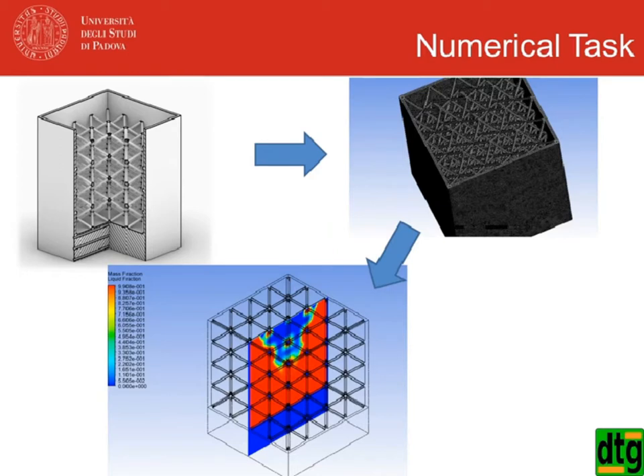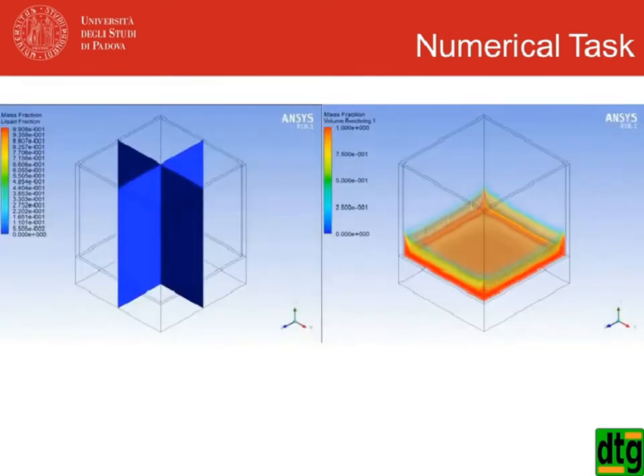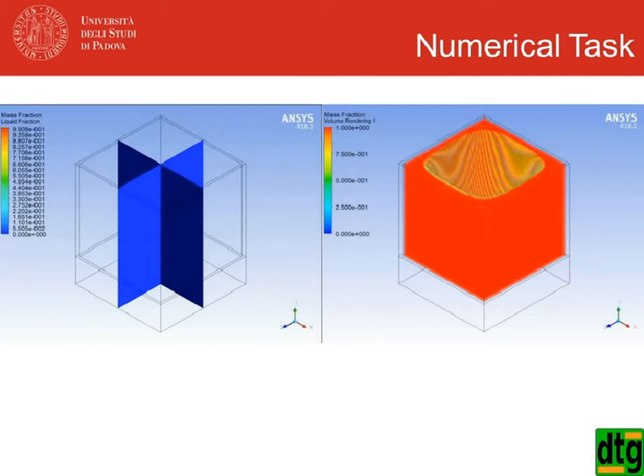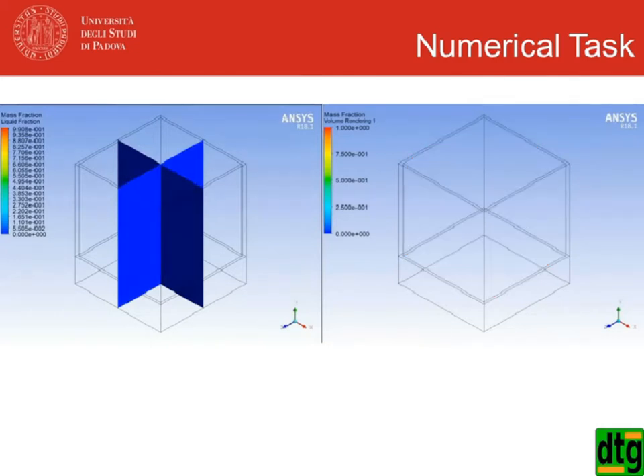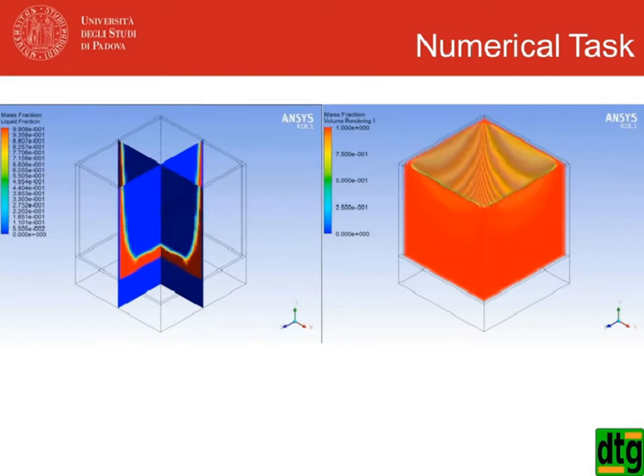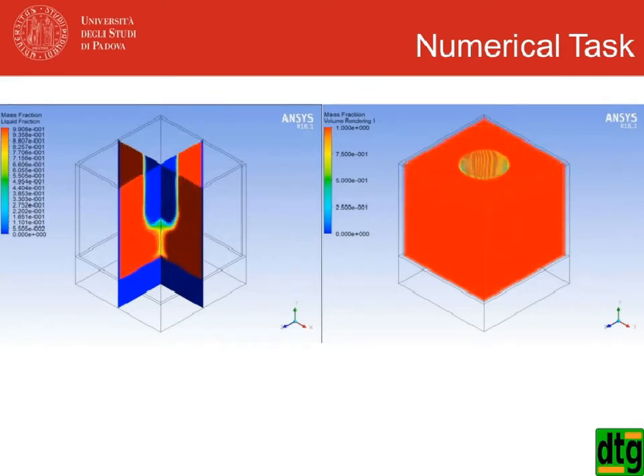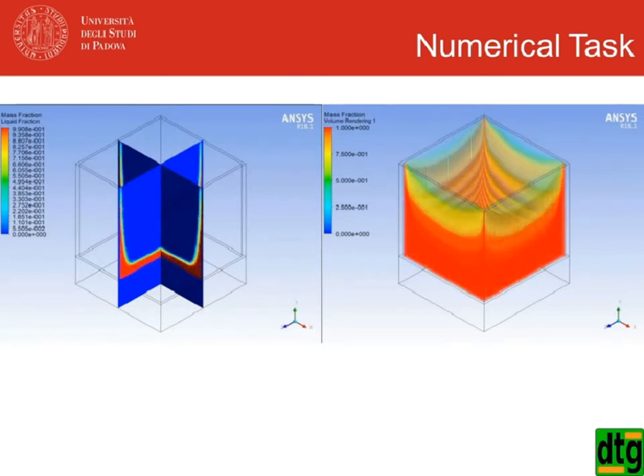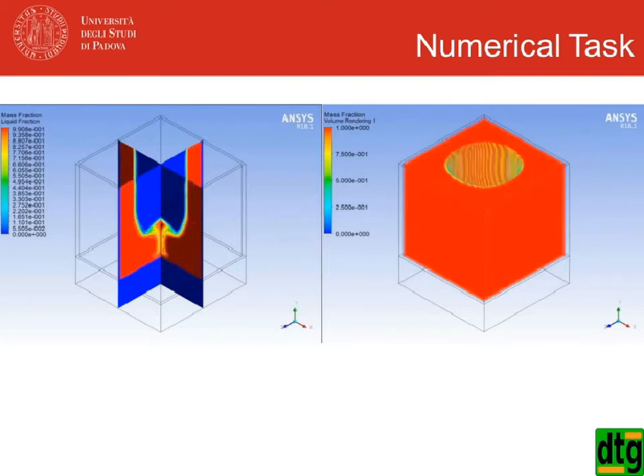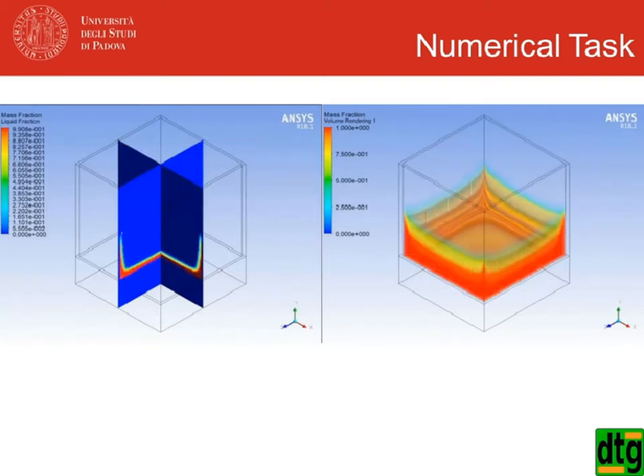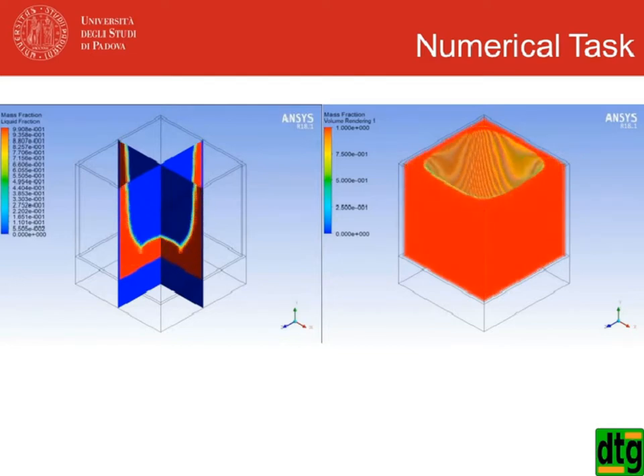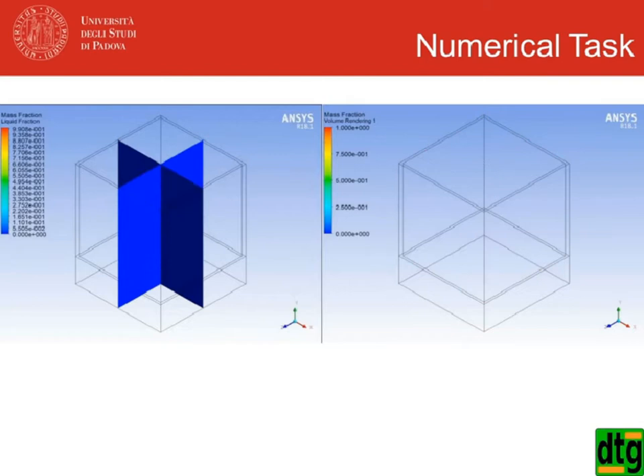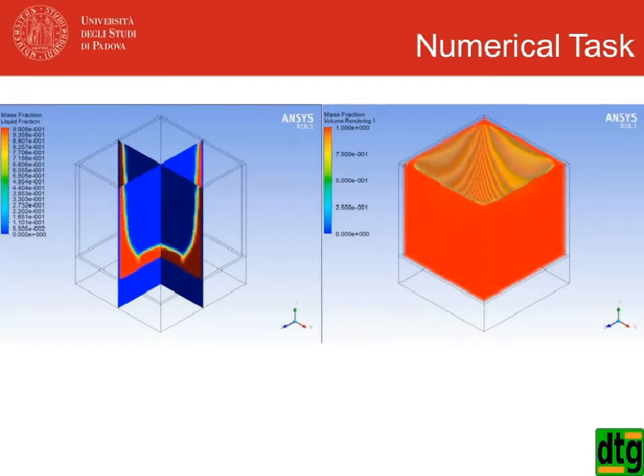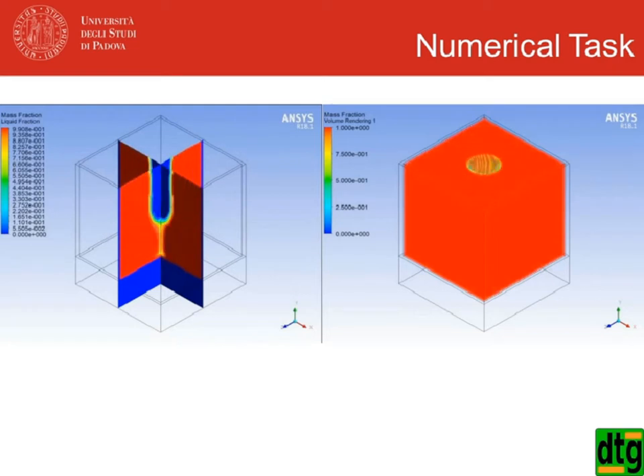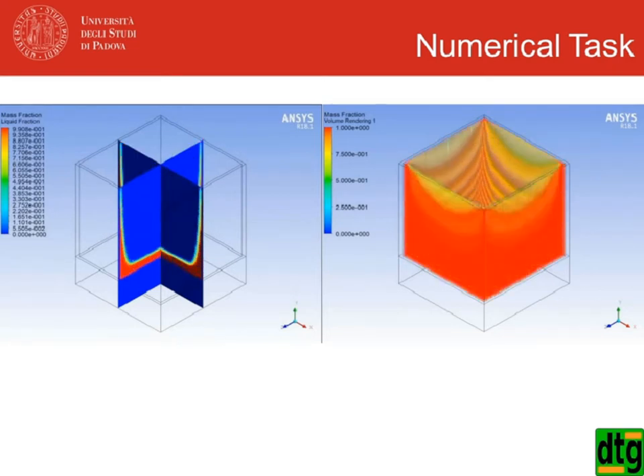So we started from the box, okay, we meshed it, and then we simulated it. And these are just a few results, if you want. So the phase change process occurs from the bottom up to the top, okay, in the empty box. And this is just a video or animation of the numerical results we obtained, and a fantastic agreement between the temperature measured in the system and, as I will show immediately after, the experimental result was obtained.